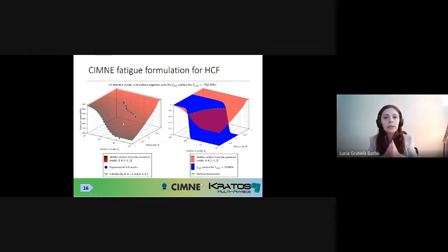So, for instance, if in a numerical simulation, in finite element simulation, you start to have damage due to fatigue, what will happen is that you will have right away a stress redistribution outside of the area where you have damage. This means that the stress state will be altered at those specific integration points inside those specific finite elements. This means that even if you begin with a stress ratio, for instance, of -1 or 0.1, you